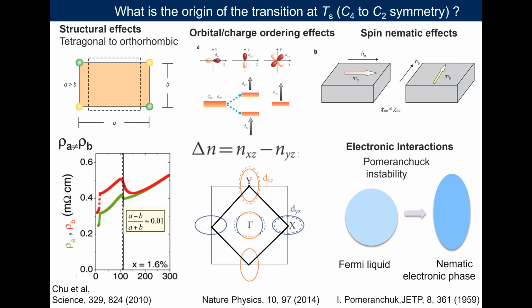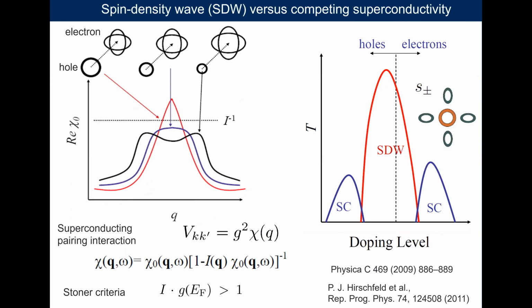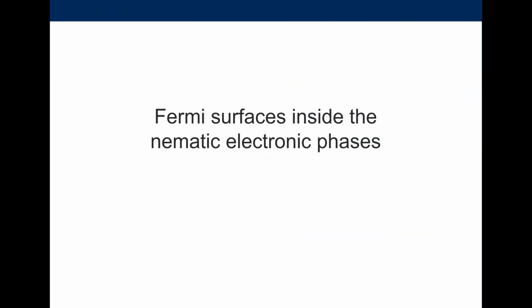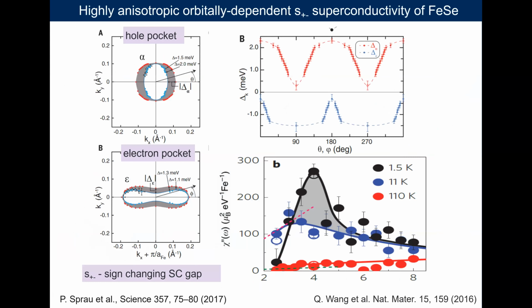I had a question about the anisotropy of the gap that you see. You mentioned that it suggests a strong orbital component or anisotropy. Does it mean that different orbital components have different signs of the gap? Is that what's important for this? So these are the STM data by Seamus Davis group. And to model the behavior, it's been proposed that obviously the Fermi surface is close to the one determined from ARPES studies. And they had to account for orbital differentiation in the interactions. So they have to assume the XY character will be affected differently from the other orbital character. But presumably they had to, was it just different sizes or was there a different sign? They use different Z values, so different, but I don't know about the signs.